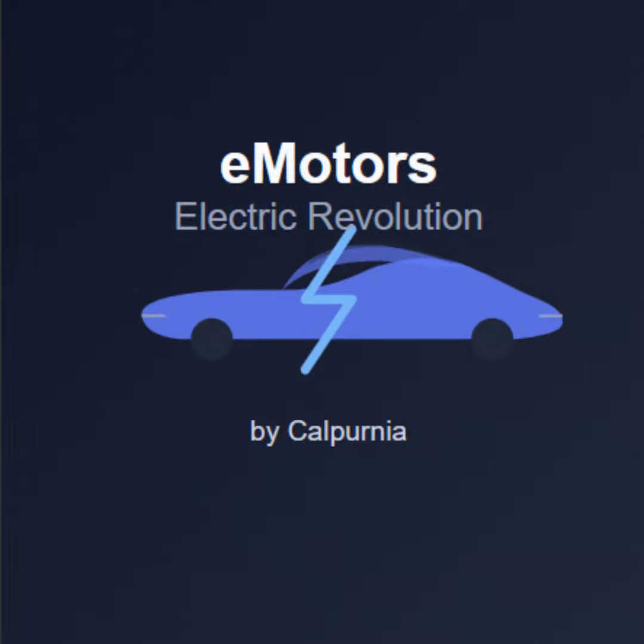Now, here's a finding from the Geotab study that genuinely surprised me because it seems a bit counterintuitive at first glance. The data showed that vehicles with really high usage, driving lots of miles per year, do not necessarily experience significantly greater battery degradation than lower used vehicles. The difference in capacity loss they found was minimal, something like only 0.25% over 4 years. Yeah, that often surprises people. Why isn't simply using the battery more, putting more cycles on it, accelerating its decay more noticeably?